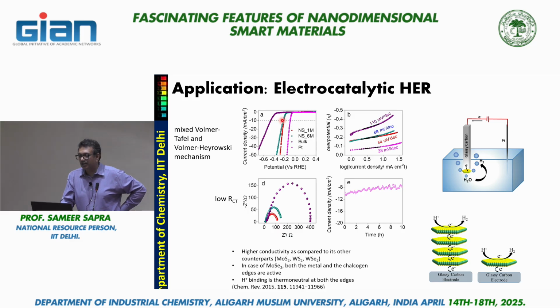to, this is 6 monolayers and 1 monolayer comparison, so don't worry about that. The moment you exfoliate it, this potential falls down drastically, and that is because you've provided so many of these sites, right? So many of the defect sites that are present on the surface after exfoliation, that your potential just drops. So you can do the same thing at much lower costs.